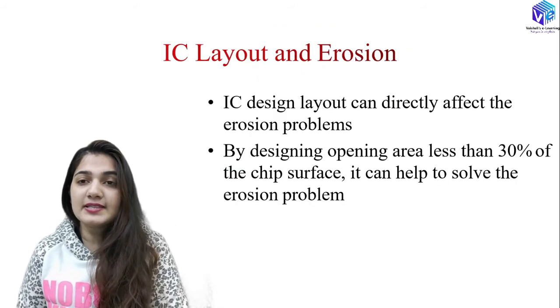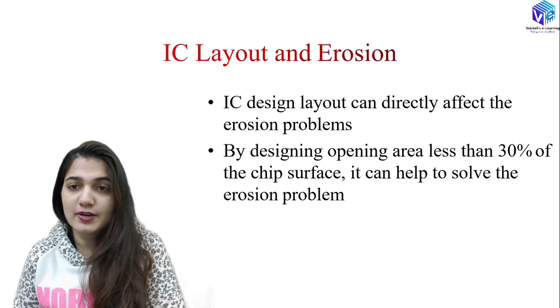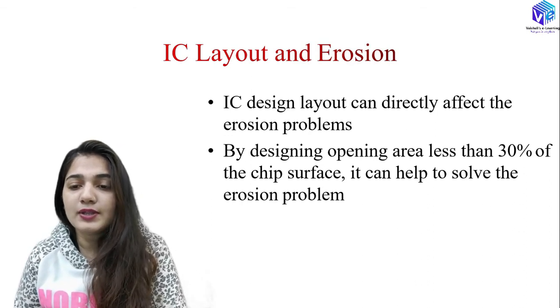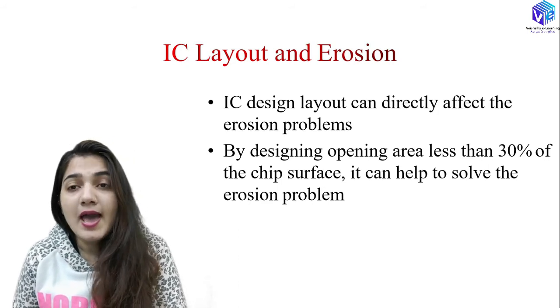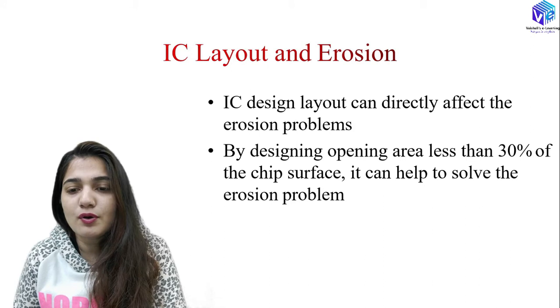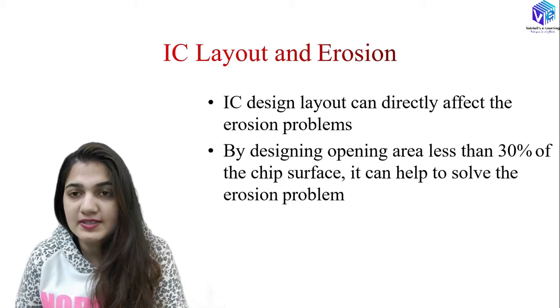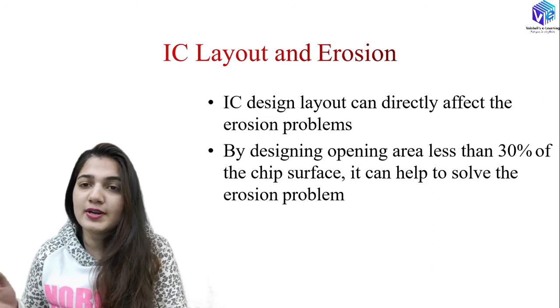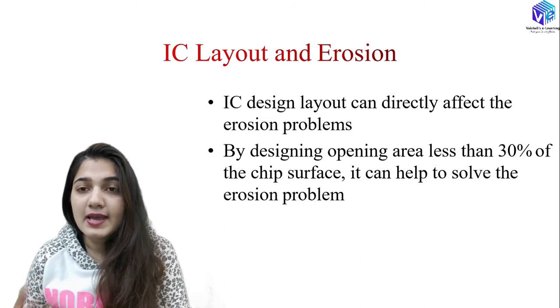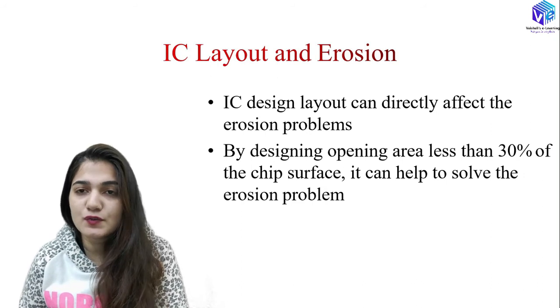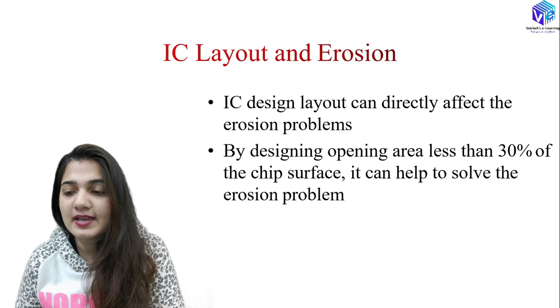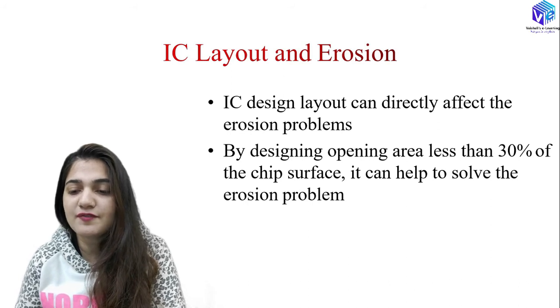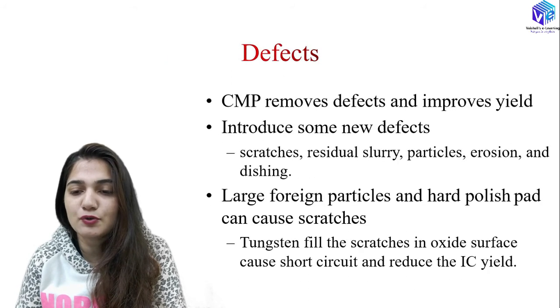IC design layout can directly affect the erosion problem. If you have more density you have less removal rate, which causes erosion. By designing opening areas less than 30 percent of the chip surface, it can help to solve the erosion problem.